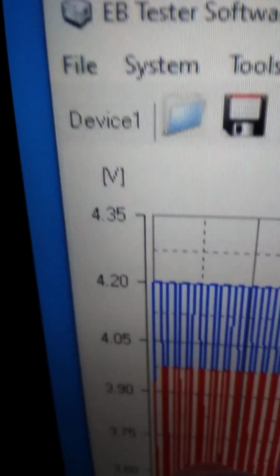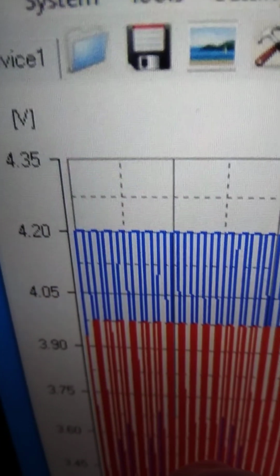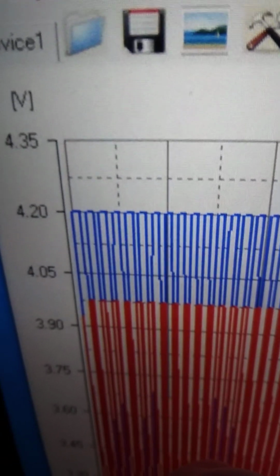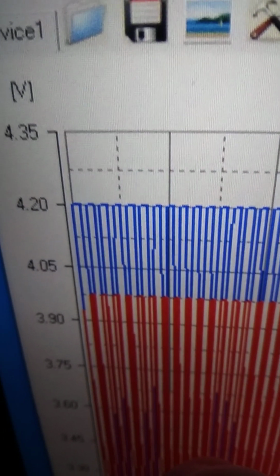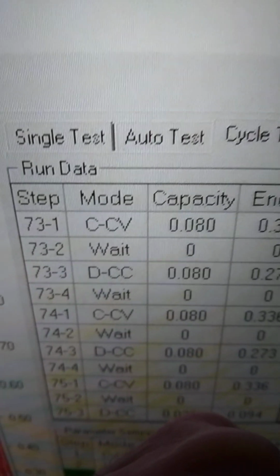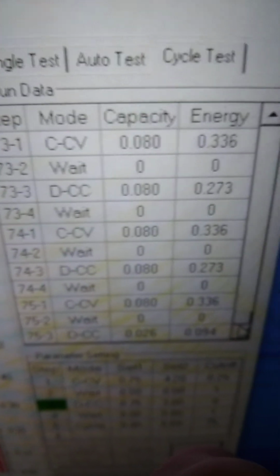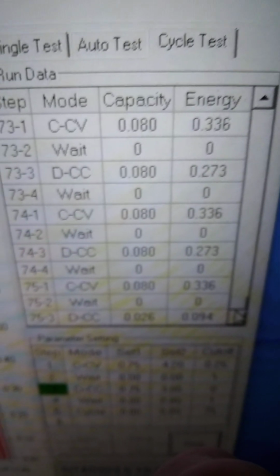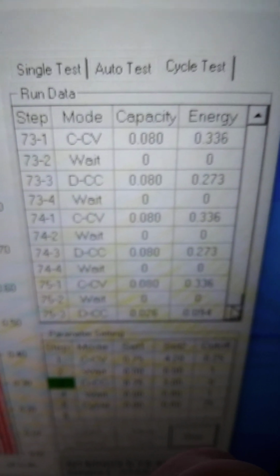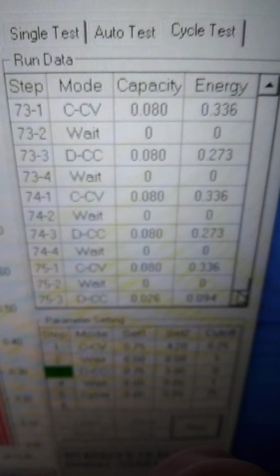4.20 volts to start. Then there's a sharp drop down when you discharge to about 3.95 volts. But the electrolyte solution is holding up. I recorded the mass before and after the run, and we're not seeing any evidence of decomposition or loss, such as chemically deteriorating the electrolyte solution, which is very important here.